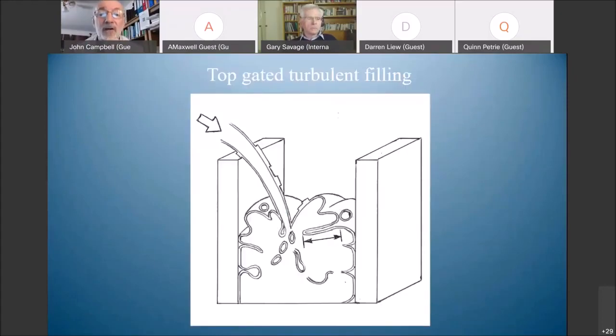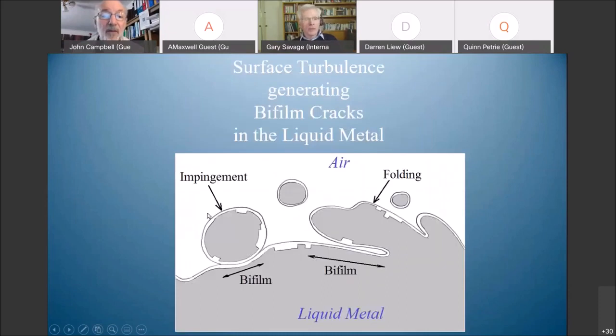So here we are. This is where our casting technology is today. We're pouring things. We're folding in this surface. We're making these bifilms, cracks in the liquid, and we're making bubbles. These are the 2 entrainment defects. And these are the kinds of things we're doing when we're impinging other drops on the surface. We impinge in a bifilm. When we fold over the surface, we fold in a bifilm. Whatever we do, bifilms are the result, and they are cracks. They are cracks in the liquid.